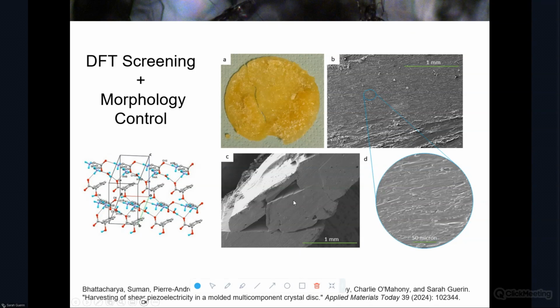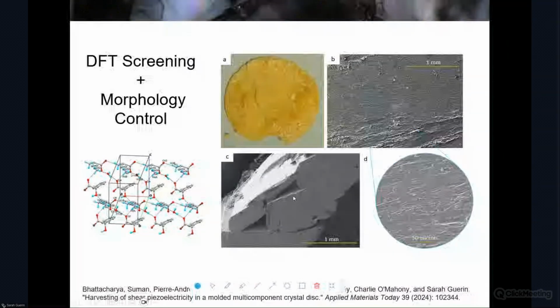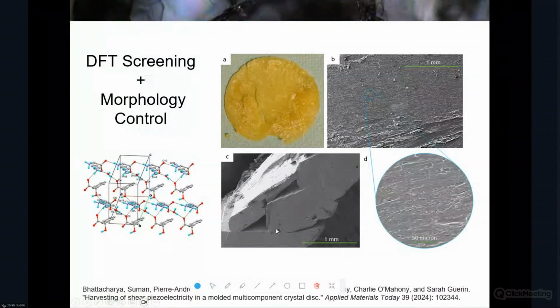The crystals in this case, they weren't perfectly orientated along the longitudinal axis that we wanted, but the way they naturally self-assembled, so if you can imagine your top electrode here along the surface, your bottom electrode here, and this crystal orientated at 90 degrees, that allows us to actually get out shear piezoelectricity. And because molecular crystals tend to have high shear stiffness, this was a lovely serendipitous, almost accident, where we were able to harness that shear piezoelectricity, but in that really easy longitudinal configuration because of how the crystals assembled. So you can see the surface here blends out into all of these kind of plate crystals. They're a bit thicker than needles that morph together to allow us to harvest unique properties.